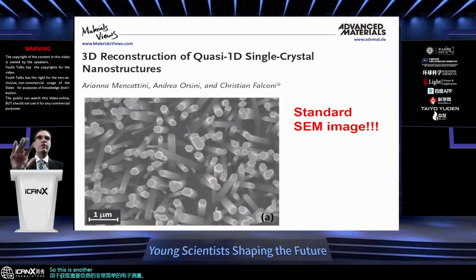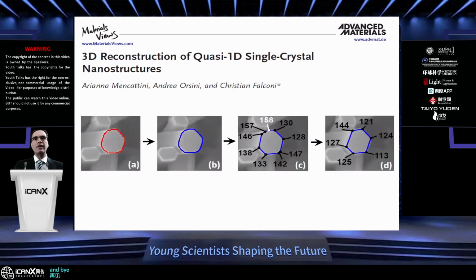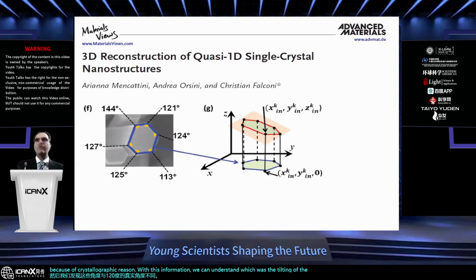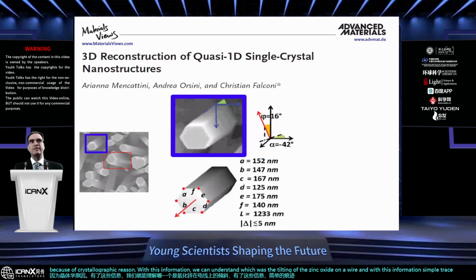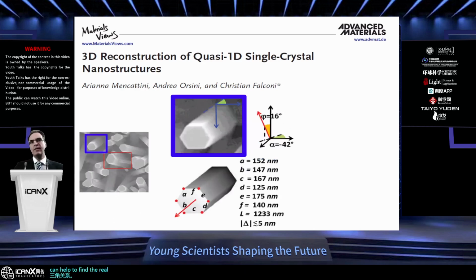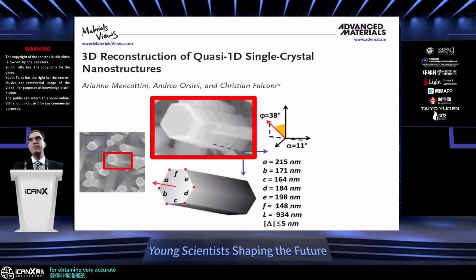This is another work where we just use conventional top-view SEM images of zinc oxide nanowires, and after some simple signal processing, we find the vertices in the right image. Then we find that these angles are different from the real angle, that is 120 degrees, because of crystallographic reasons. With this information, we can understand the tilting of the zinc oxide nanowire, and simple trigonometric relations can help find the real, exact dimensions of the nanowire. So that's just what a conventional scanning electron microscope can do for obtaining very accurate dimensions.